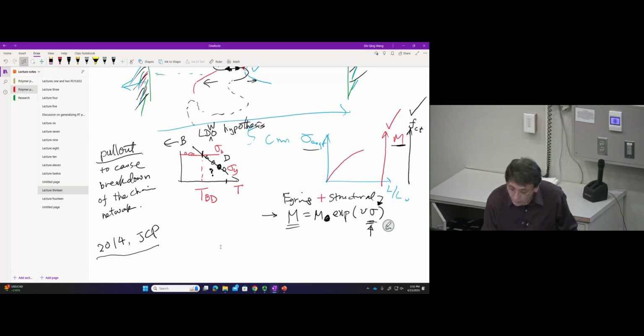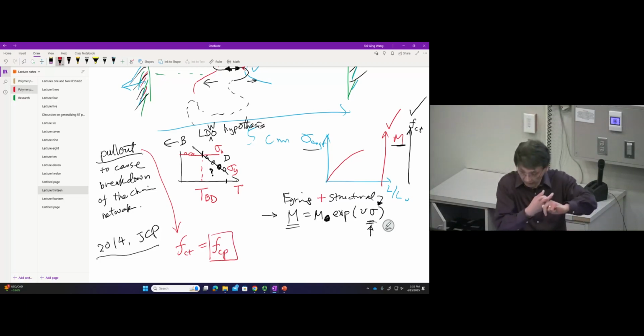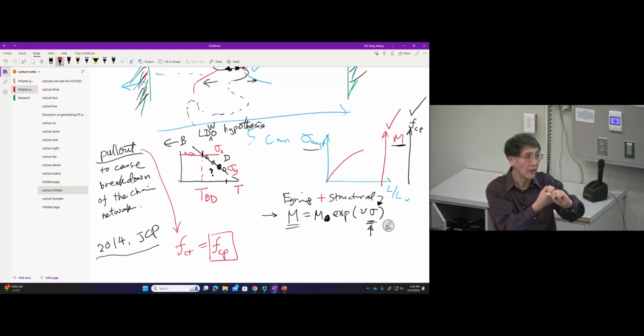The reason you have a pull out is because the chain tension has reached the level that we call chain pull-out force. So it's a certain amount of tension in the chain you must reach before sliding can occur. The effect of the solvent is now interpreted as lubricating that interaction, so the chain pull-out becomes easier. That's the interpretation.